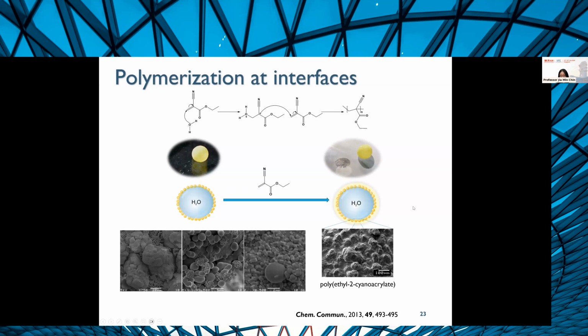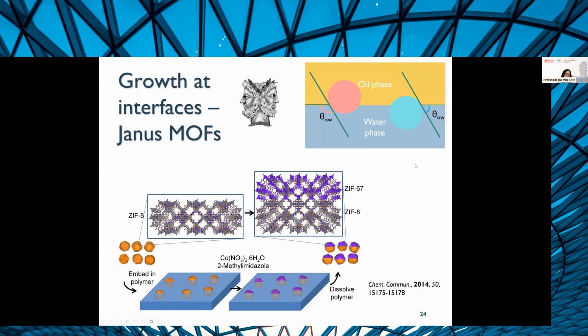So we've shown that we can use in situ reactions also at interfaces to functionalize these materials. Now we thought, okay, we've used air-liquid interfaces for growth as well as polymerization. What about liquid-liquid interfaces? I always wanted to make Janus MOFs because this would allow us to make little micromotors. And so this is one of the first examples, really the second example of a MOF micromotor, but the first one using these Janus MOFs.